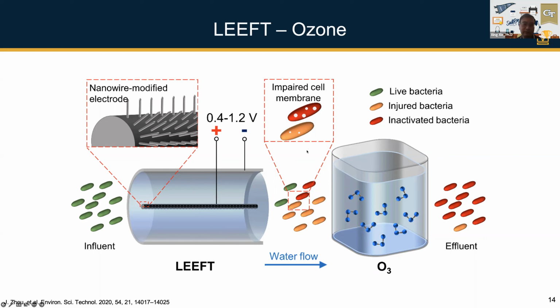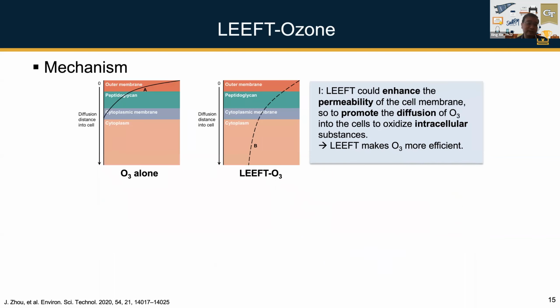So ideally, you can save the ozonation dosage, right? The basic mechanism is that if you just do ozone alone, it needs to oxidize and break through the cell membrane, and then eventually this can be a diffusion curve for the ozonation. So it takes some time. The ozone needs to damage basically all the cell structure and eventually get into the cellular components.